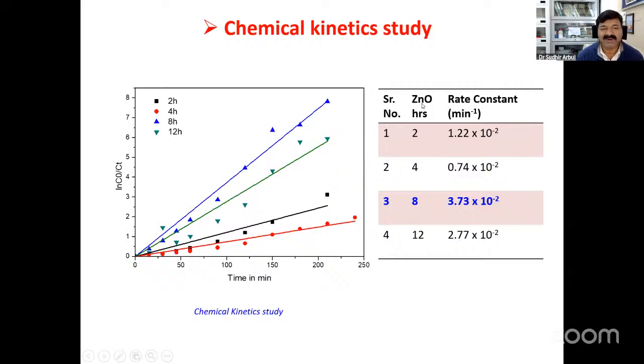See here, whatever zinc oxide prepared at 2 hours, its rate constant is 1.22 × 10^-2 per minute. This rate almost becomes 3 times more, 3.73 × 10^-2. Or this rate I can compare with earlier other scientists' data. So this kind of study can be performed using UV-visible spectroscopy.